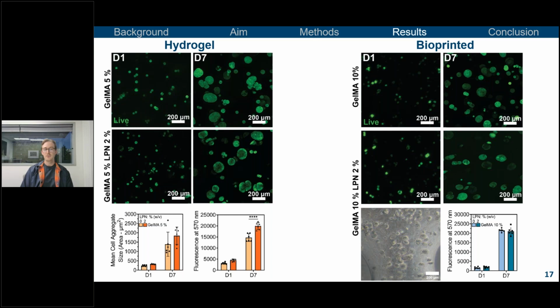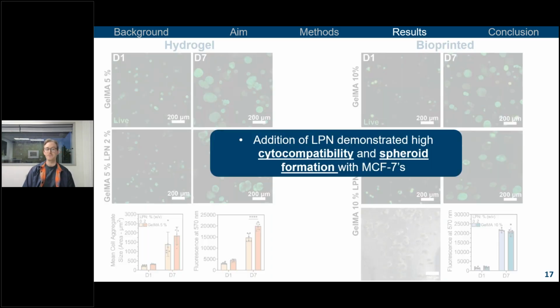We then translated this to a more bioprinting application, using a higher polymer concentration of 10% for printing purposes, replicating the same experiment and showing that when you change with the printing process, you're able to generate these large spheroid formations, which were indeed metabolically active and comparable to the controls also. So this showed that the addition of LPN demonstrated high cytocompatibility, comparable to our controls, and generation of these spheroid formations using the breast cancer cell line.